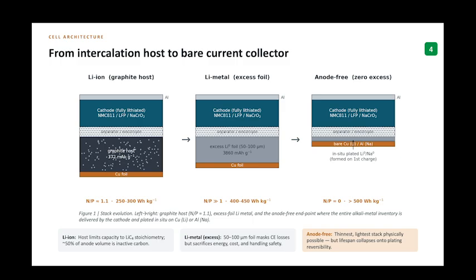In the middle, you do see lithium metal with excess foil. The 1980s approach is still used by some solid-state players. You bolt on 50 to 100 microns of extra lithium as insurance because the cell wastes a little every cycle. Works, but you paid the insurance in weight, cost, and a very spicy manufacturing process. Lithium foil and ambient air, that doesn't go along. On the right-hand side, you do see the anode-free system, the tiniest stack physics allows. Cathode, separator, and bare foil. Every lithium atom lives in the cathode on day one.